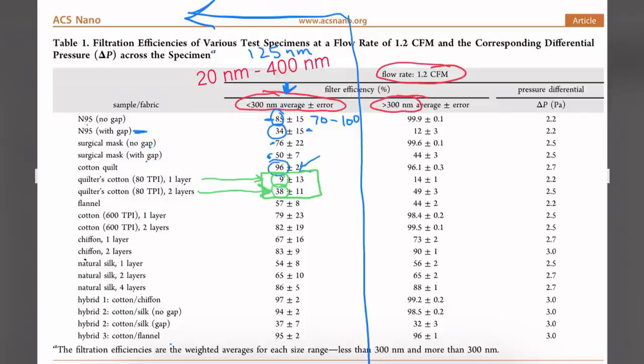Flannel is at 57 percent. Cotton 600 threads per inch: 79 and 82 percent whether you use one layer or two layers. Now chiffon was not mentioned initially. We were told to use 100 percent cotton fabrics. Chiffon is not cotton - in this case 90 percent polyester and 10 percent spandex chiffon. There was a 67 percent filtration rate on only one layer of this very thin fabric and an 83 percent rate on two layers of chiffon. Silk ranged from 54 to 86 percent depending if you used one, two, or four layers of natural silk from the silkworm.